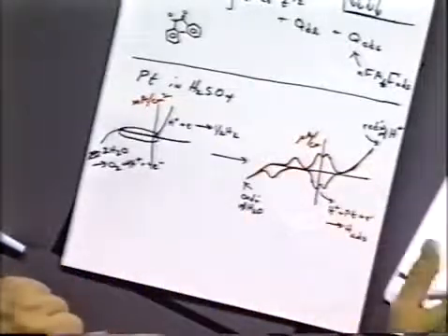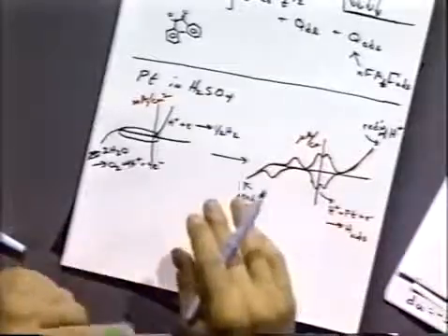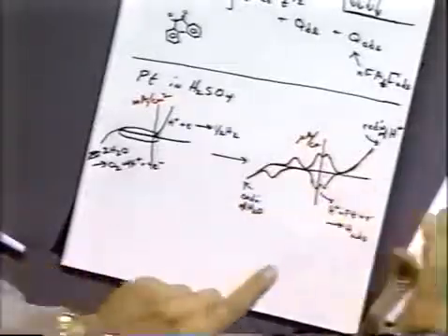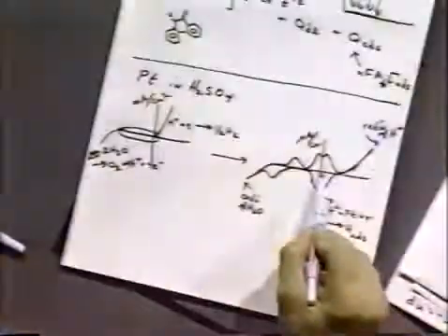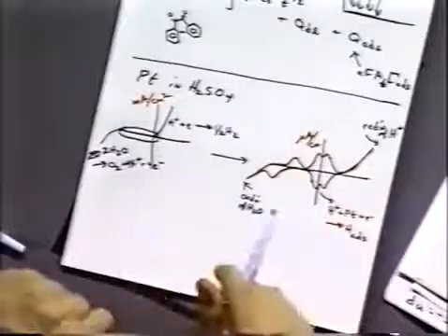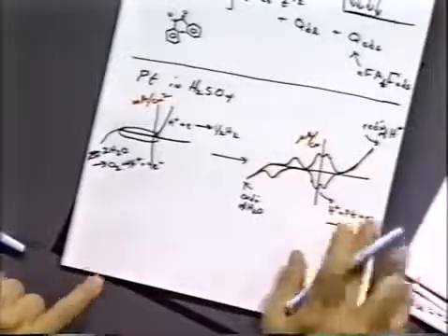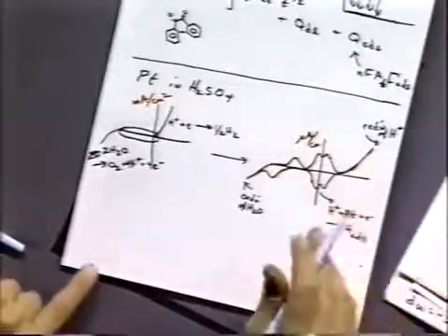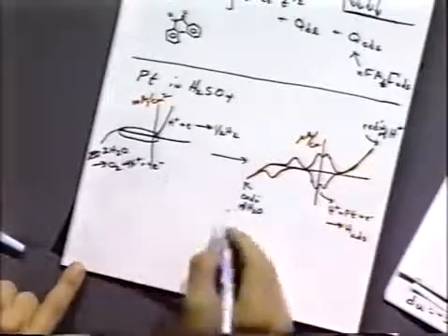Now, as soon as the monolayer of adsorbed hydrogen atom is formed, the current can no longer flow because we're not allowing that reaction to occur anymore. So we get 0 current then. But by looking at the charge under these peaks, for example, you can get the amount of hydrogen that's adsorbed on the surface and understanding a true idea of the real area.